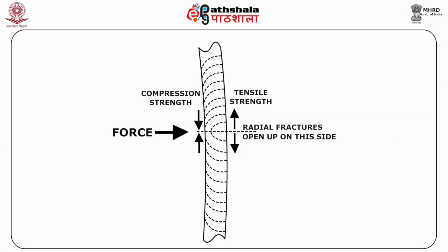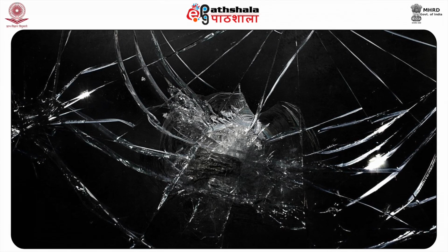Radial fractures. Radial fractures will always travel along the path of least resistance, and they will always end if they encounter an existing fracture line. This fact allows an investigator to determine the order of multiple impacts to a single pane of glass.